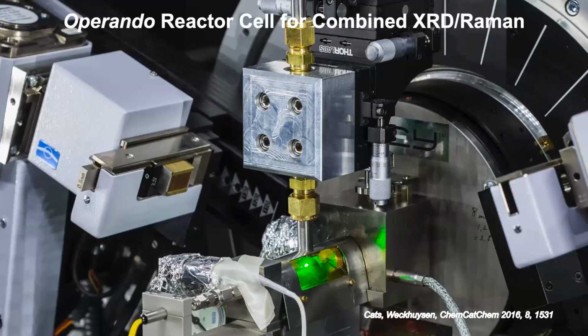We have been using this system and added Raman to it. So here you see the cell on the bottom where you see this green, and here we actually have the laser coming in. By the way, we also can do it with UV-Vis, can actually add any method from the top. We did methanol to hydrocarbons with UV-Vis, and with Raman we have been following the Fischer-Tropsch reaction.